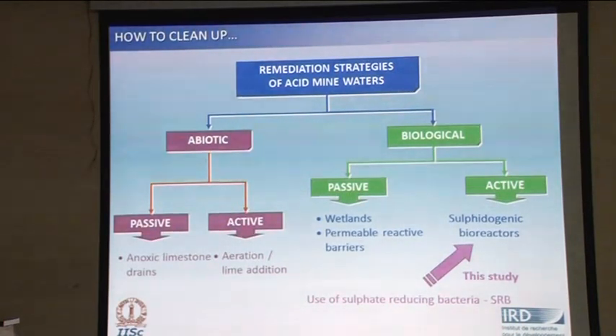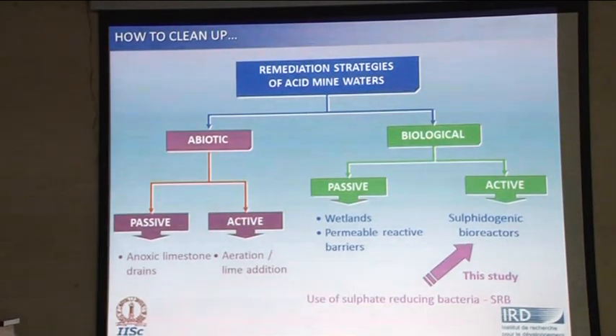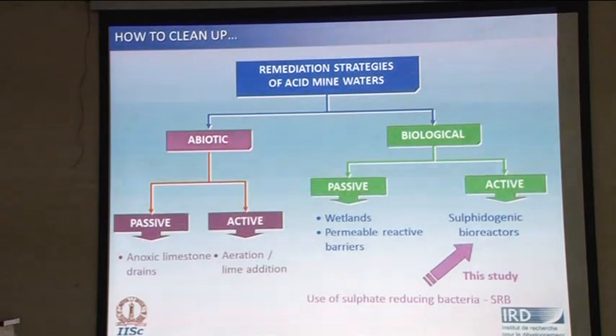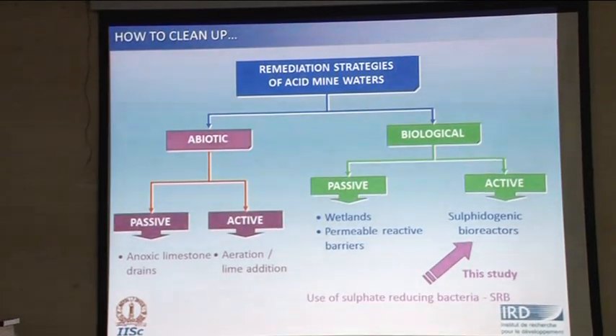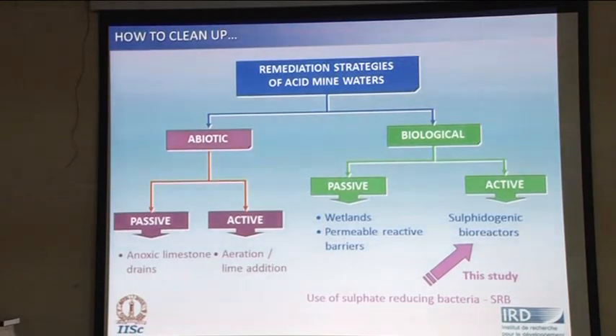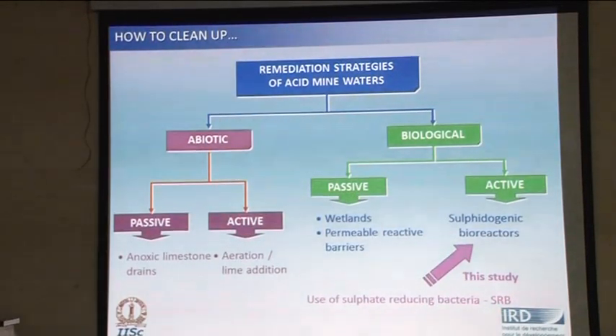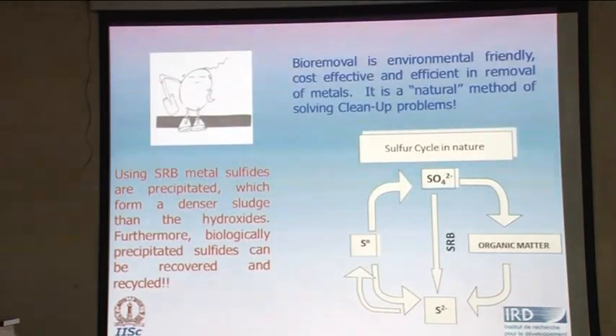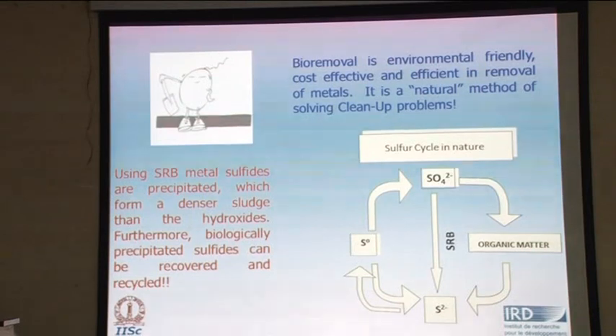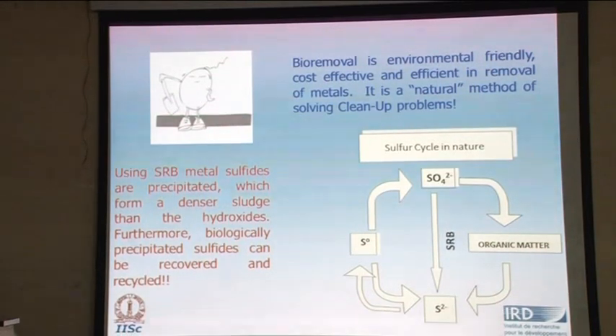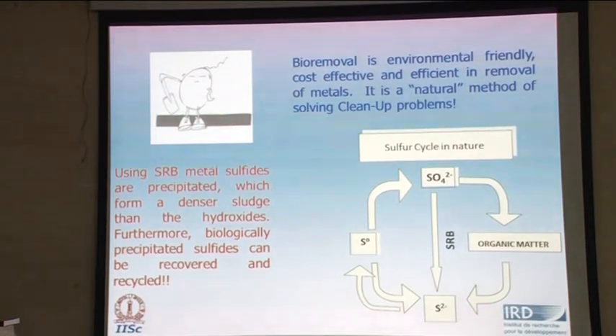What we have adopted in our study is to look at the role of the sulfate reducing bacteria, because the ions which are present in the effluents are basically as their sulfates, because the sulfuric acid is converting the copper, lead and zinc into the corresponding sulfates. So we were wanting to know whether this sulfate could be reduced to the sulfide using this sulfate reducing bacteria. So this is the strategy in nature. You have the sulfur cycle. So in terms of leaching, you need to oxidize the sulfide to the sulfate. But in terms of an environmental issue, when you already have a sulfate, you have to reduce it to the sulfide. And this is what we do.